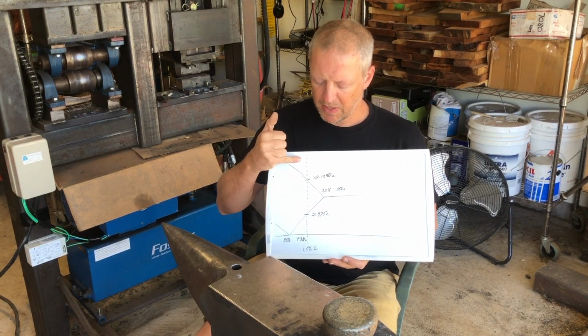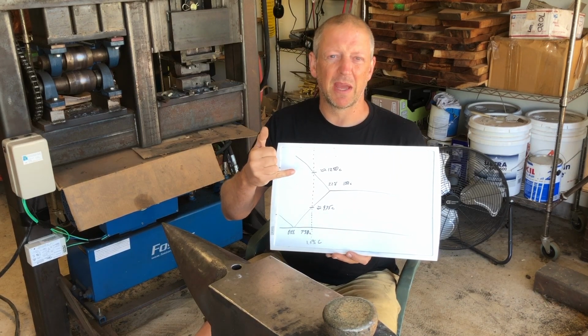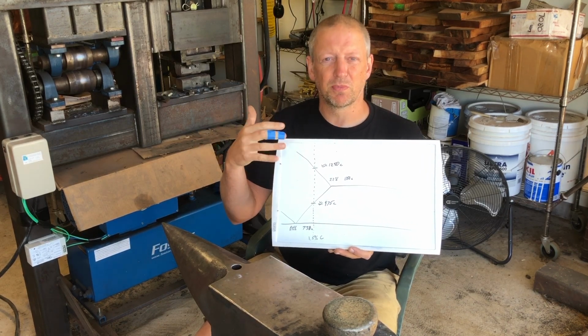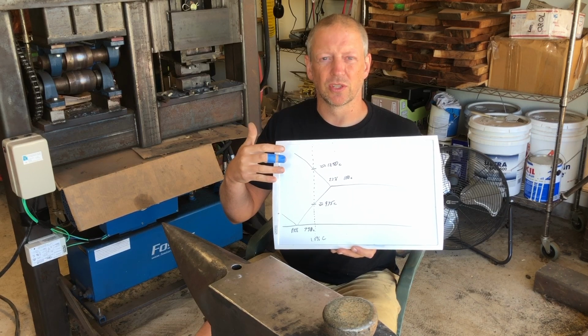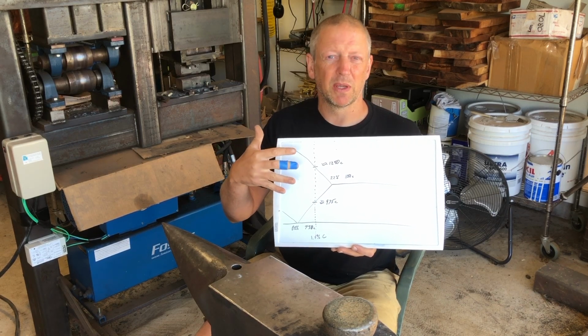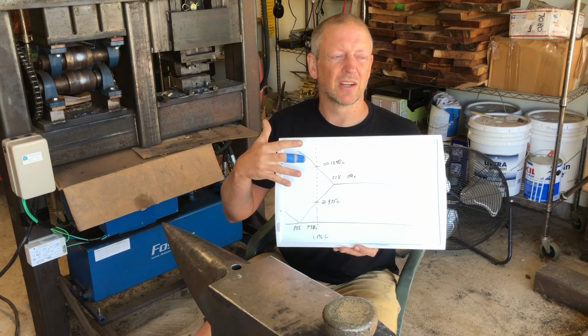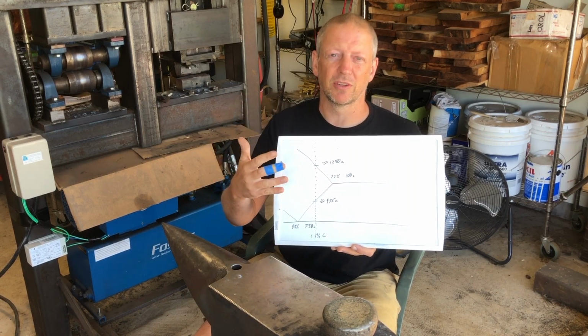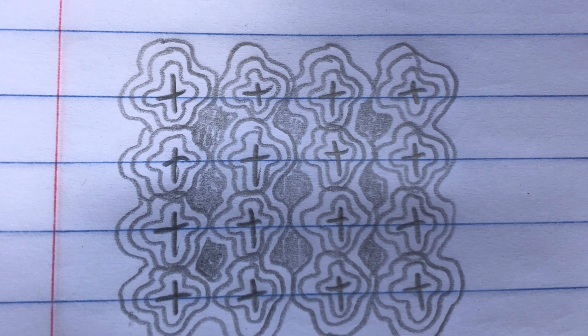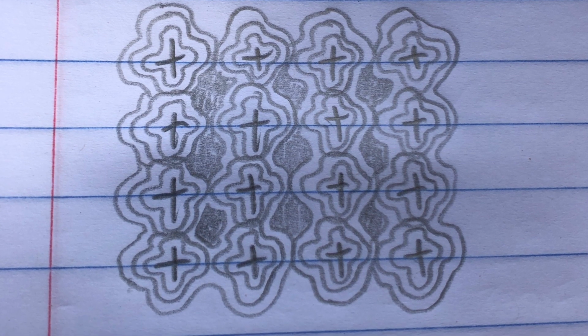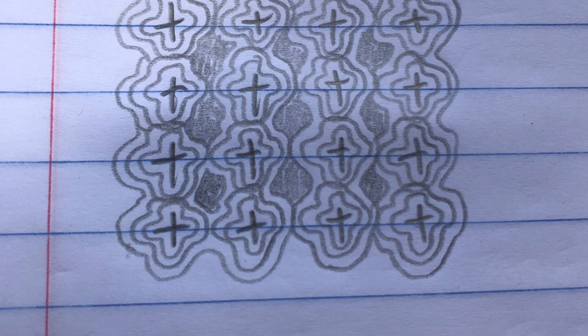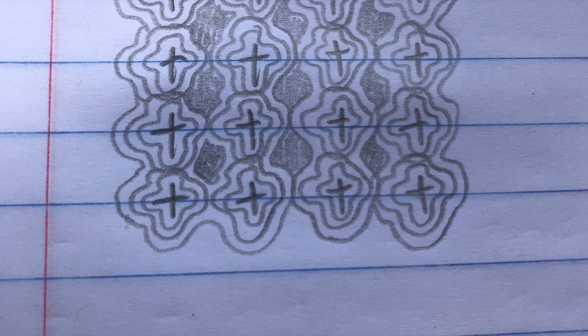So basically, the best way to imagine it is that you have this almost pure iron dendritic structure that is growing, and then it is trapping a higher concentration of almost every other element in between. In this illustration, the dendrites are growing towards us, and we can see that the T-shaped dendrites in the center successfully grow in layers outwards, eventually trapping the darker, higher concentration material in between.